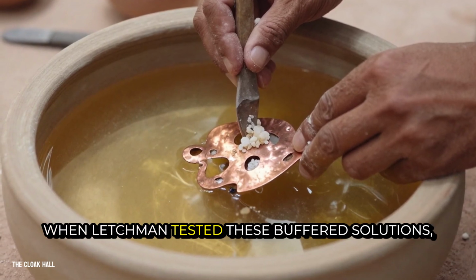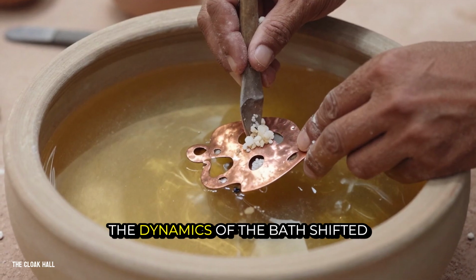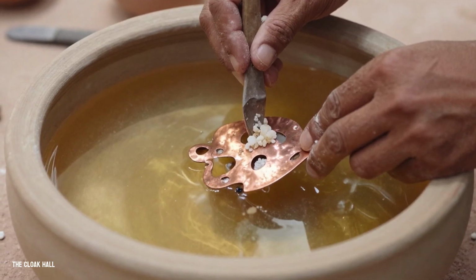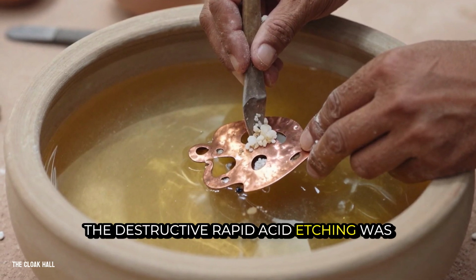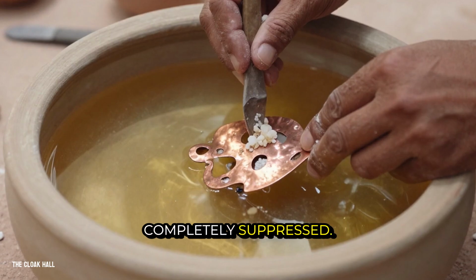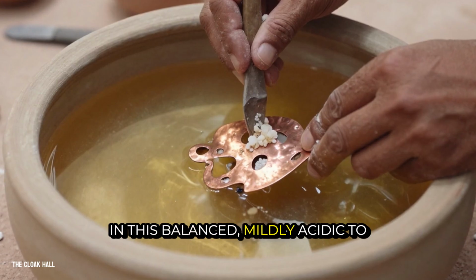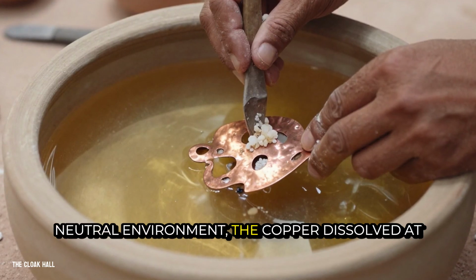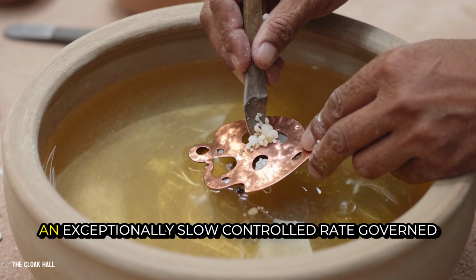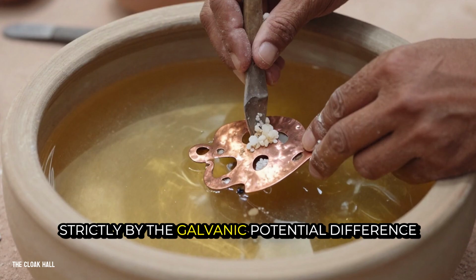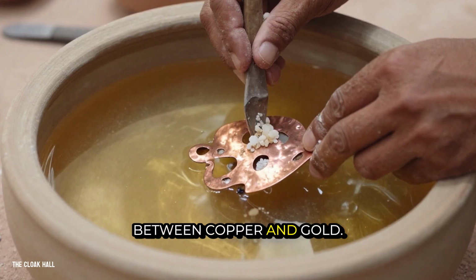When Lechtman tested these buffered solutions, the dynamics of the bath shifted entirely. The destructive, rapid acid etching was completely suppressed. In this balanced, mildly acidic to neutral environment, the copper dissolved at an exceptionally slow, controlled rate, governed strictly by the galvanic potential difference between copper and gold.